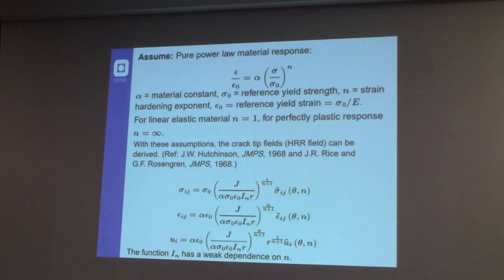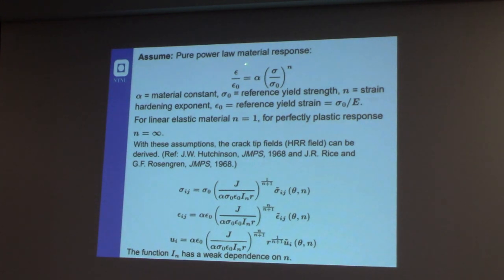But what is very interesting is that you can express the stress field of the material generally in terms of the J integral, and according to elastic-plastic rules for your material that is no longer linear but follows a kind of power law rule, where n is the hardening exponent of the power law expression of your material.